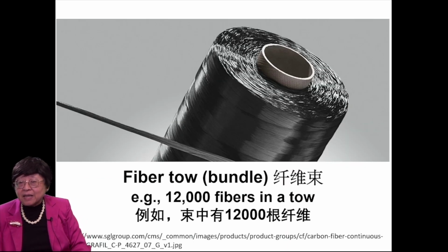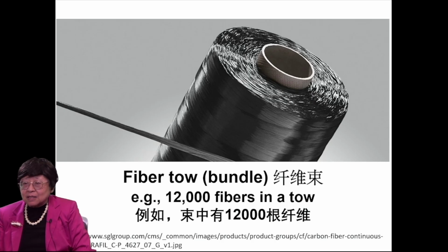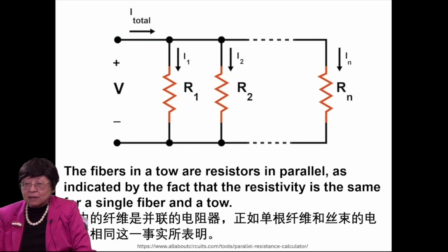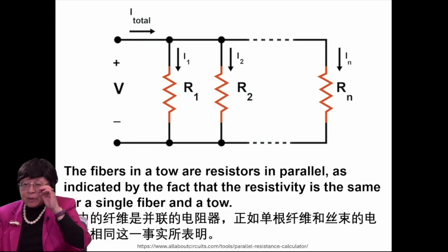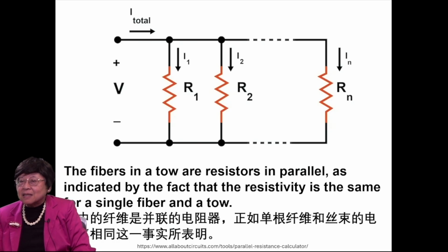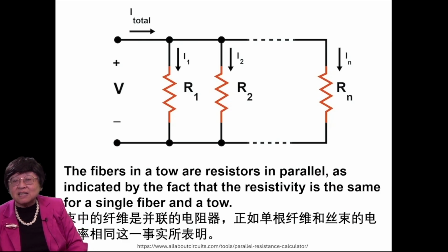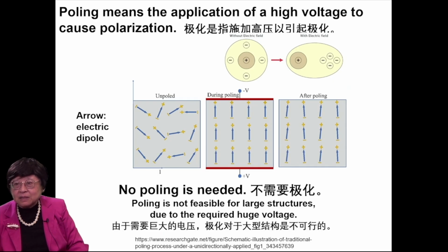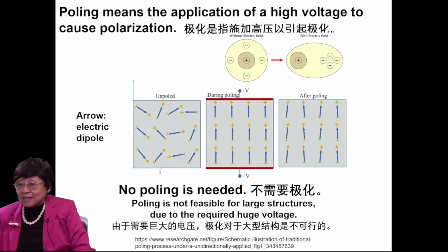Now, here again is a fiber tow, such as 12,000 fibers in a tow. The fibers in a tow are resistors in parallel, as indicated by the fact that the resistivity is the same for a single fiber and a tow. Now, poling is not needed. And all I talk about doesn't involve poling.